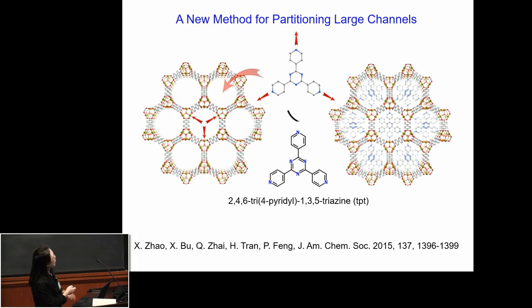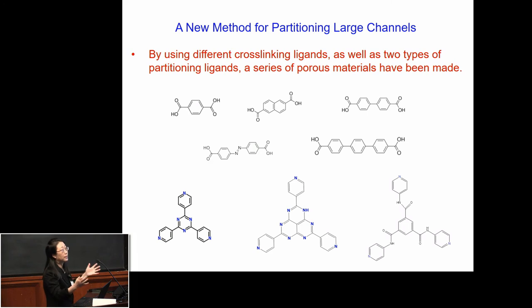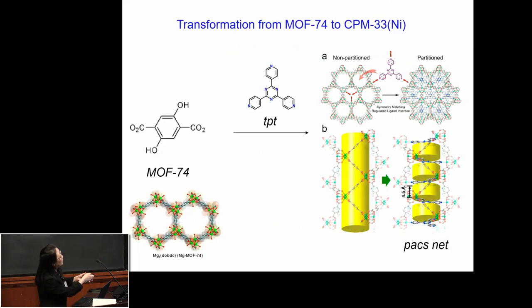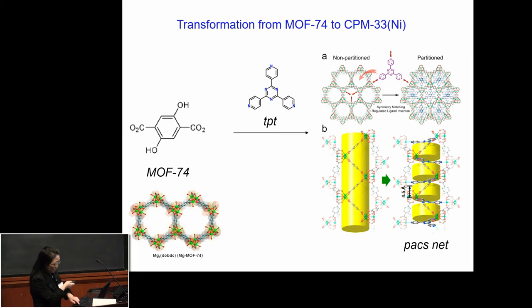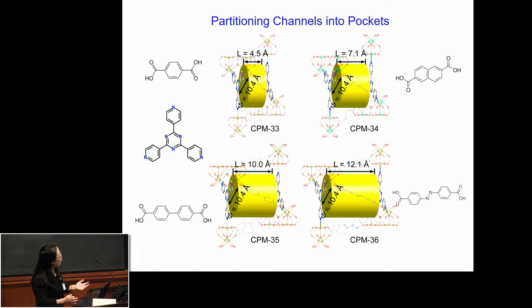This structure was solved by single crystal analysis. We then used the TPT ligand — much more stable, with C3 symmetry — which coordinates with the three metal sites in the channel to divide it into different domains and introduce different functionality. This is a great achievement. We can synthesize these materials with different partition ligands to tune pore size and channel dimensions. Looking along the C direction, we divide the channel into three different pockets and also chop the straight channel into segments by the TPT ligand. The length of each cylinder segment is determined by the cross-linking ligand, while the diameter is set by the partition ligand.